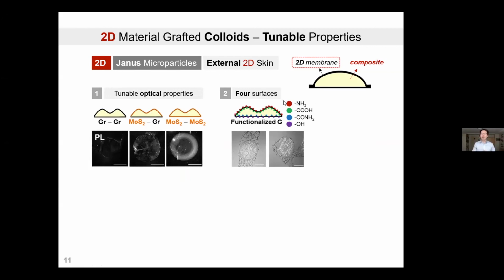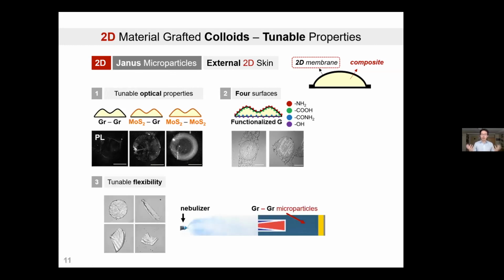So you can actually, using our fabrication method, control, either covalently or non-covalently, what kind of functional groups you can adhere to the surfaces of these different layers of 2D materials. By doing so, we can control the mechanical flexibility of our particle. You can make them strong enough that they will stay in this pancake shape, or you can roll them up into a burrito or like a taco shell.